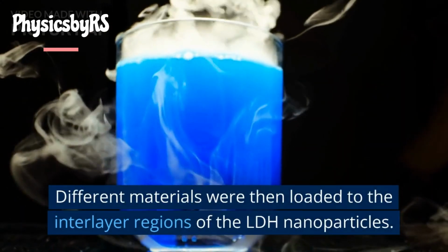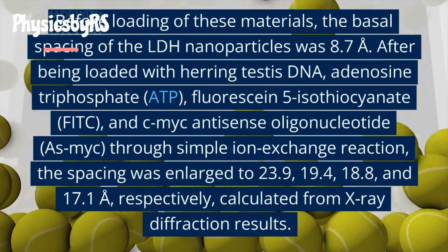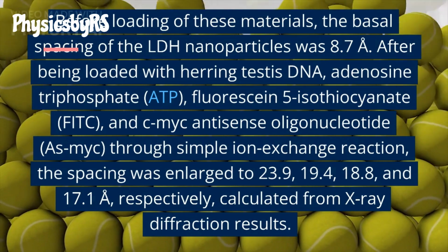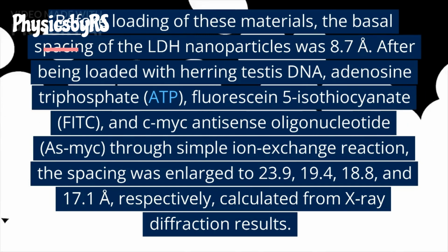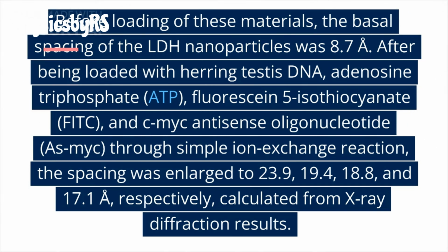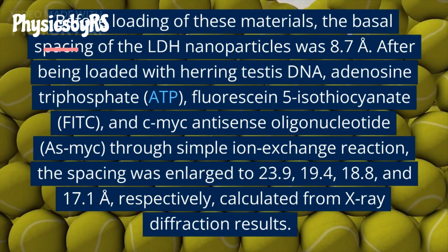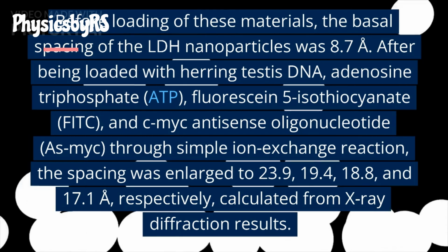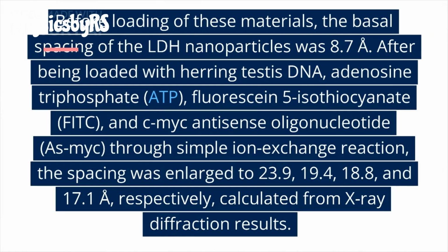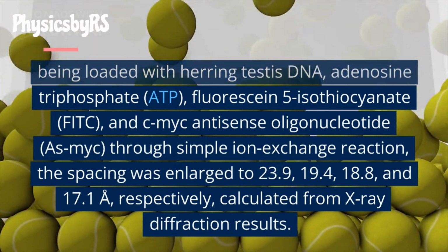Different materials were then loaded to the interlayer regions of the LDH nanoparticles. Before loading of these materials, the basal spacing of the LDH nanoparticles was 8.7 Å. After being loaded with herring testis DNA, adenosine triphosphate, ATP, fluorescein 5-isothiocyanate, FITC, and c-myc antisense oligonucleotide, as-myc, through simple ion exchange reaction, the spacing was enlarged to 23.9, 19.4, 18.8, and 17.1 Å, respectively, calculated from X-ray diffraction results.